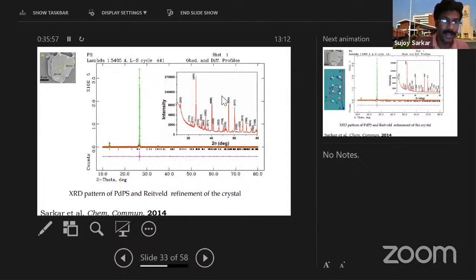With this XRD data, we analyzed using a known method called Rietveld refinement. With this data analysis, we found that this is the experimental and this is the theoretical. The theoretical data is dotted, and this is the difference between theory and experiment. We found that there is not much change between the two. Only the reflection change is there, but that is because they studied a single crystal and ours is a polycrystalline material. So from this we can say that our material is polycrystalline.